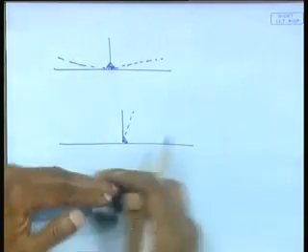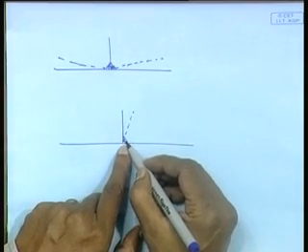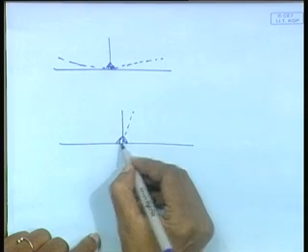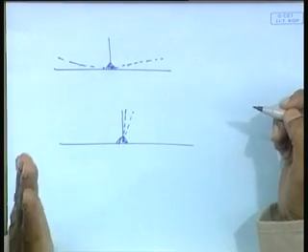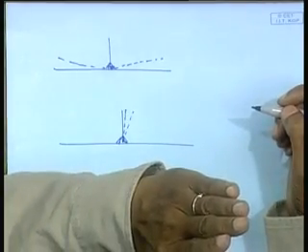Or in this case, the plate is restrained and the vertical member or the stiffener is welded. If I weld from one side, it bends, deforms like this. Then I weld the other side, it comes back, but not to the original position. It remains deflected in the previous position. Why? Because it has become restrained. One side now has been welded, so the forces will not be enough to bring it back to the original position.